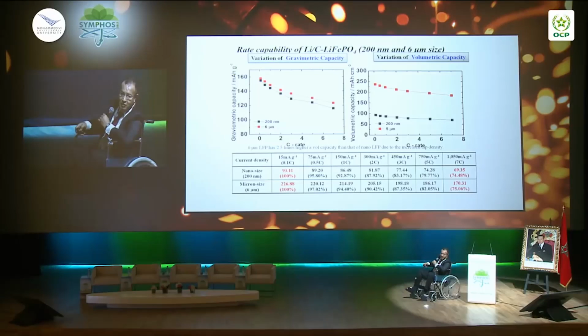So how about the power? Because that's very important. If the power is not that great, then we don't have a case. And here is the gravimetric capacity versus C rate. When you charge and discharge at very high rate, and this is with the nano versus micron, you see they're almost parallel. Very, very close. So we did not affect the power capability of this material.